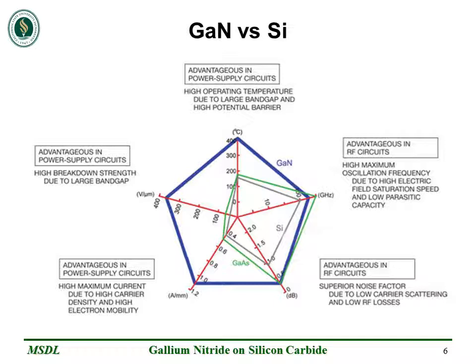This graphic unfortunately does not include a comparison for silicon carbide, but it provides a great visual for how well silicon measures up to gallium nitride. Silicon is represented by the inner gray lines, while gallium nitride is represented by the outer blue lines. Silicon comes somewhat close to the performance of gallium nitride when we consider maximum oscillation frequency and parasitic capacitance, but gallium nitride performs far better when we consider high power, high temperature, high current applications.